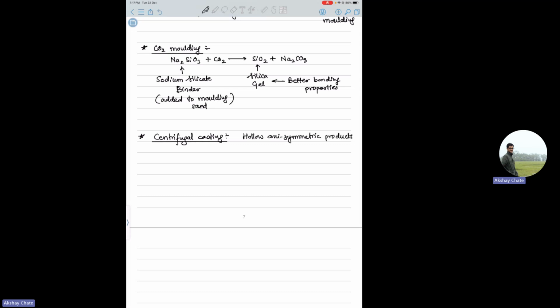So you use centrifugal force for casting, and therefore you will have variation in your cast properties in the radial direction. That is also one disadvantage, that you will not have uniform properties when you do centrifugal casting. Other than that, because heat transfer from the outer surface is more than the inner surface, you'll have finer grains outside and coarser grains towards the inside of the casting.